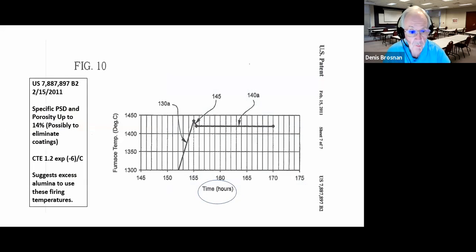Now, of course, Latchman's patent was pretty old, and here's a 2011 patent. And in that patent, a specified pore size distribution is given. A certain firing strategy is given to get us above the peritectic temperature briefly and then cool off. Okay, and maintain a certain temperature for a period of time. I don't know if you want to believe these hours of soak or not, but you might. That's up to you. So nevertheless, this was an interesting patent.